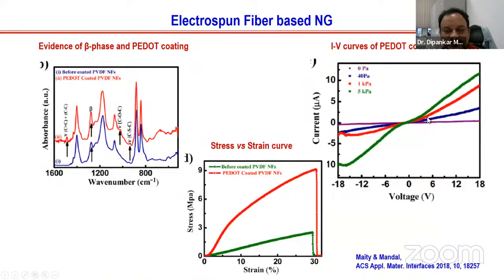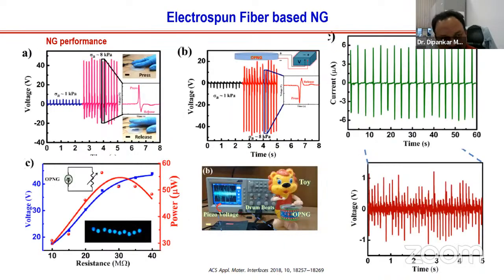Then we measure the IV curve and the stress-strain curve, and we also show from FTIR spectroscopy that we have a piezoelectric phase. This is the characterization technique where we can identify the piezoelectric phase. Vibrational bands are the signature of piezoelectric phase formation. That means another take-home message is that the electrospinning technique can induce piezoelectricity because of the strain generation. That is interesting.